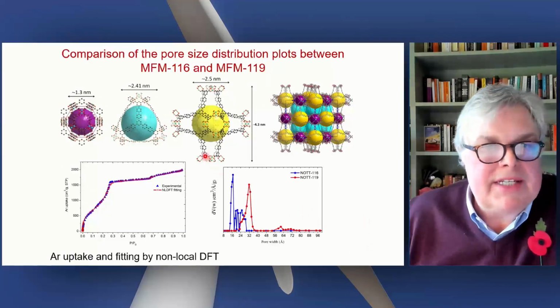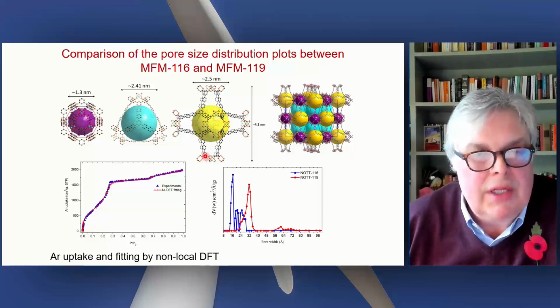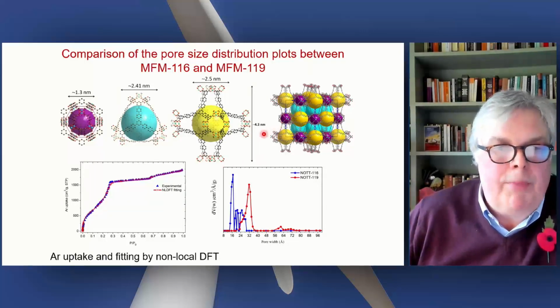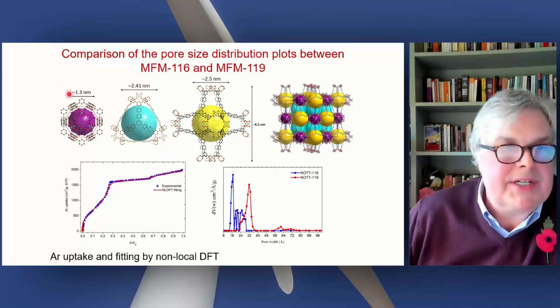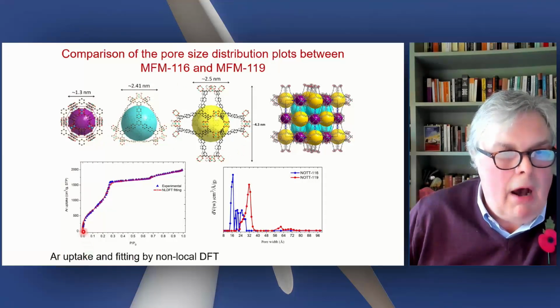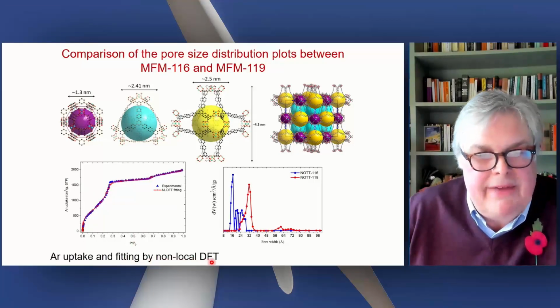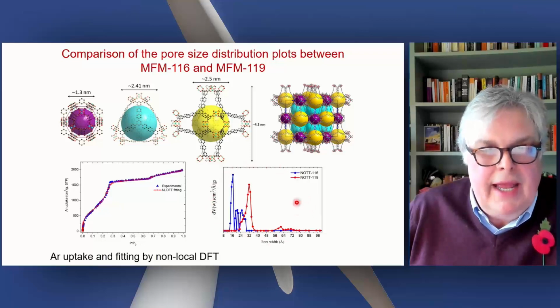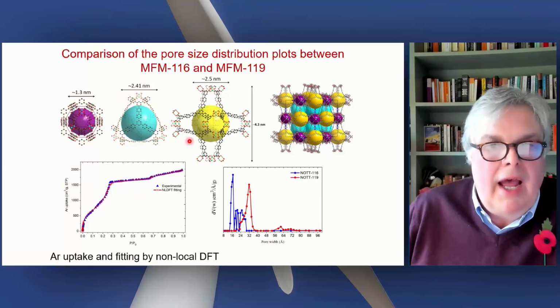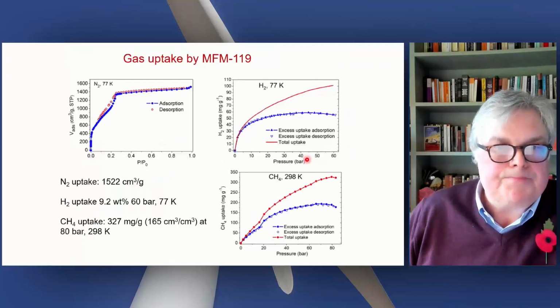And the net result is a range of isostructural materials, all of them porous with different pore diameters. You can tune these distances. You can look at, in this case, the argon uptake and then model this by non-local DFT calculations, and you get a plot of what the pore diameters and the pore width look like. So this is 119, which is a particularly long elongated ligand. And as you can see, it's heading towards being mesoporous.